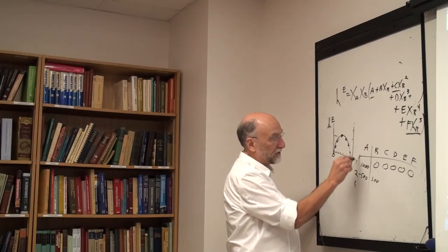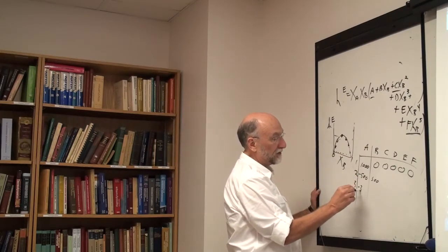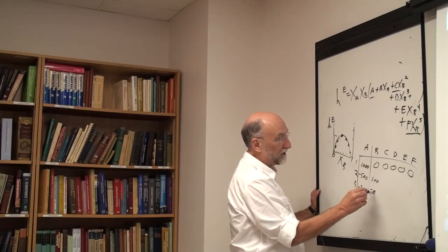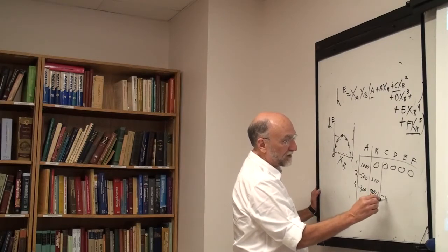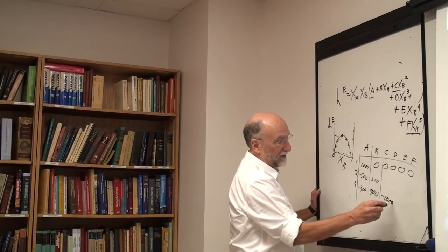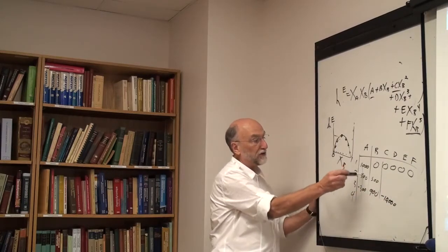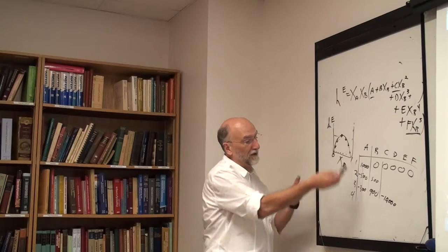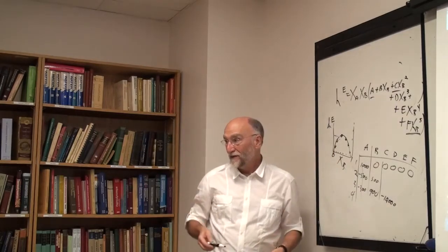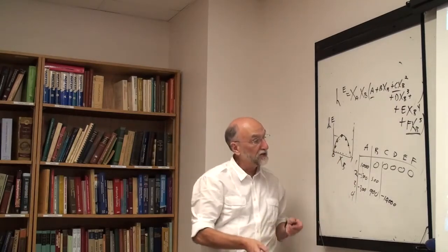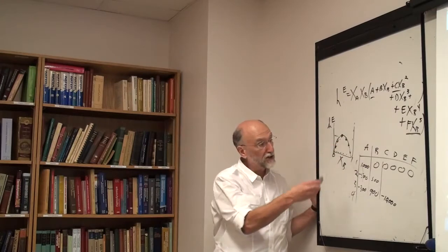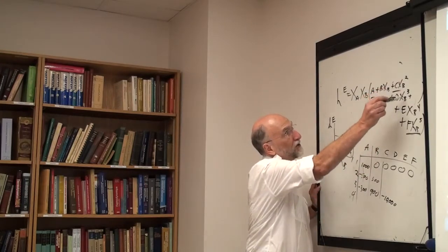And then I try to fit to three terms. Now I'll find this will go to something like 300. This might go down to 900, and this term here will go up to minus 10,000. And then I fit it to 4 terms, and these terms get bigger and bigger, and there's no correlation. The first term's numerical value can be anything. It doesn't remain constant at all. It's just a fit, because these functions are all correlated.